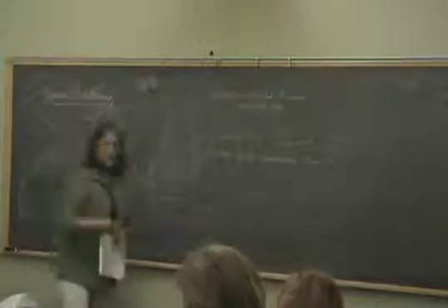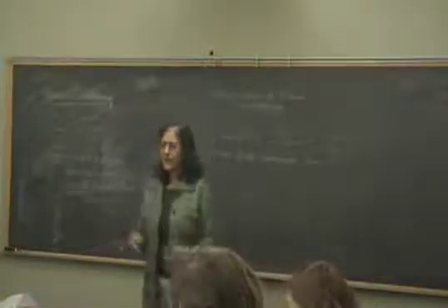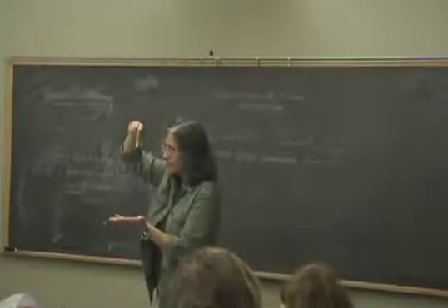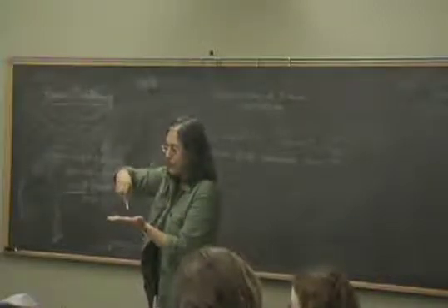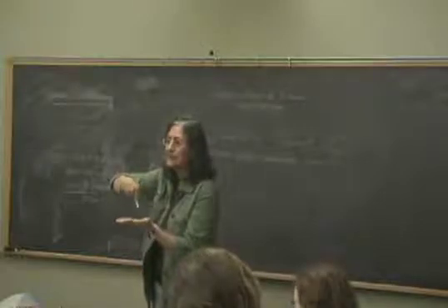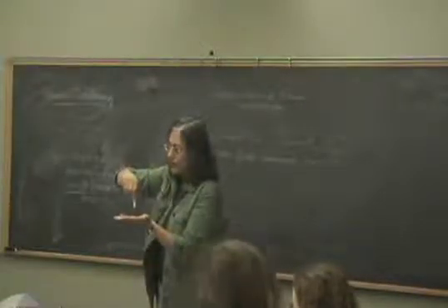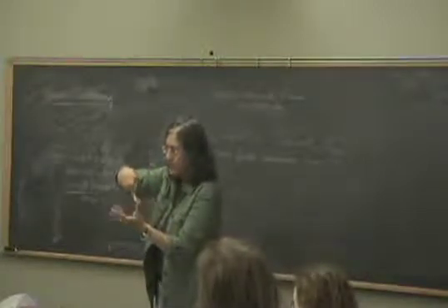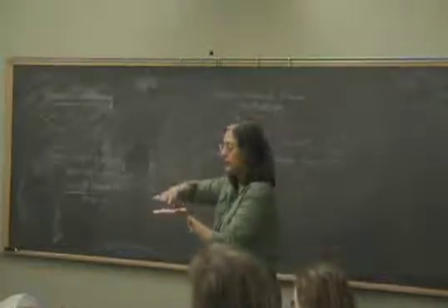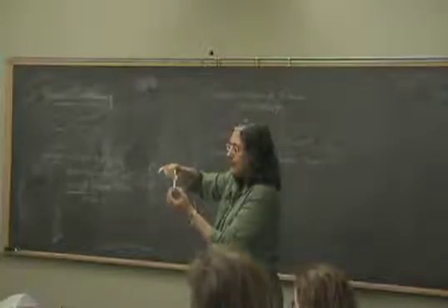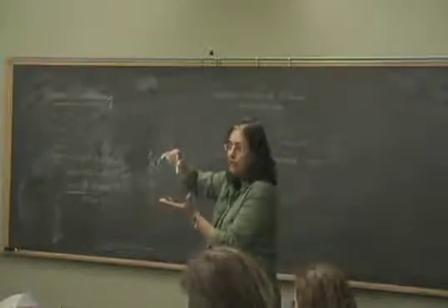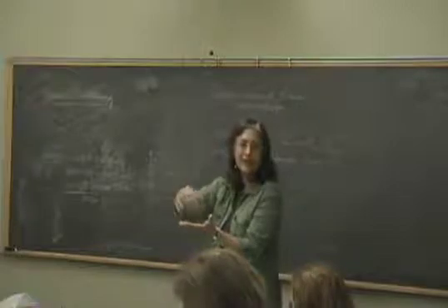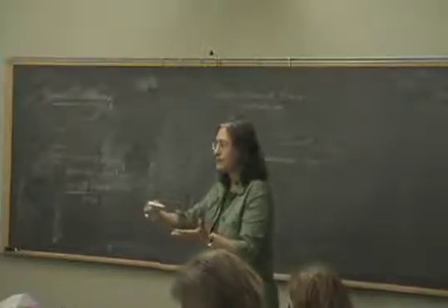And so what people do is, I don't know, maybe you do that in your lab. We talked about scanning tunneling. At that time we were bringing a tip to tunnel into some system, but now you can bring the tip just to do inelastic light scattering. So you can use the tip as a very strong electric field probe of your molecular vibrations. Here's the idea: you have some molecule sitting here, and you bring in a tip, and the electric field at the tip point is extremely enhanced because of this lightning rod effect. And that electric field now excites modes in your molecule, and you can get Raman signals.